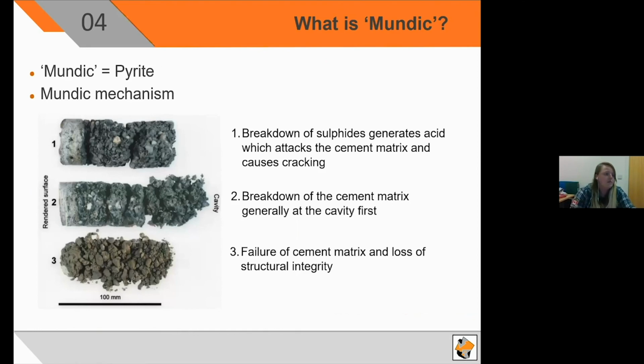So what is Mundic? Mundic actually translates to pyrite. It's a Cornish term, so it's theoretically the Cornish pyrite problem. The mechanism is the breakdown of sulfides, which generates acids attacking the cement. This breaks down the cement matrix, usually at the cavity first and outwards, and then you end up with the complete loss of structural integrity.